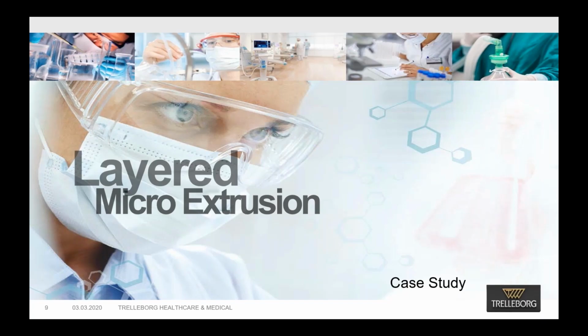Some multi-component extrusions consist of concentric radial layers for mechanical improvement and to create biocompatibility when the inside might need to be slick to insert a wire, while the outside needs to possess the maximum biocompatibility from a medical grade silicone. This same layering can be used to slow the permeability of an additive in the inner layer if it is intended to elute slowly through the outer layer.